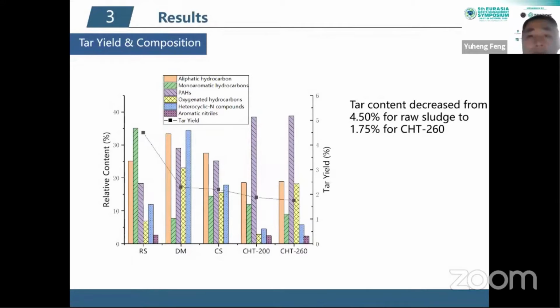For the tar yield, we could find that by the calcium oxide addition, the tar content decreased from 4.5%, and for the CHT 260 it is reduced to 1.75%. So it is largely reduced by the calcium oxide addition and also by the hydrothermal treatment.